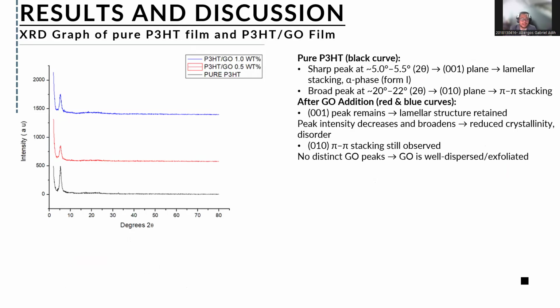So here's the XRD graph of the polymers and polymer composite. We start with the pure one, which is the black curve. A sharp peak will be found at 5 to 5.5 degrees, which is the 001 plane and lamellar stacking, the alpha phase of the polymer poly-3-hexylthiophene. Then the broad peak will be at 20 to 22 degrees, which is the 010 plane, which is also the pi-to-pi stacking. After GO is added, which is the red and blue line curves,